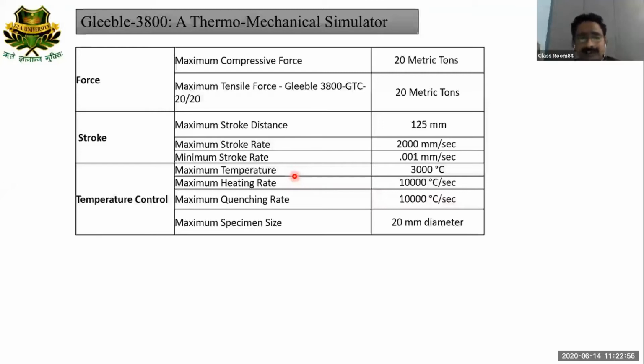I'm not considering this for the hot compression test, because in the hot compression test there is a standard that there must be a ratio of diameter and height. If you consider the diameter as 1, then the height must be between 1.2 and 1.5. For example, if the diameter is 10 mm, then the height must be between 12 mm and 15 mm. So this is the standard size recommended by the Gleeble system.